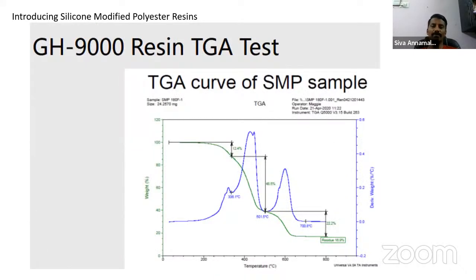This is called a TGA graph. Basically, we test the samples at multiple temperatures. For example, we start from 200 degree and end at 800 degree. When we do this test for the silicone modified polyester resin, the top is 100, meaning 100% weight of the polyester. Then the green color line, you follow only the green color line, not the blue one. Follow the green line.